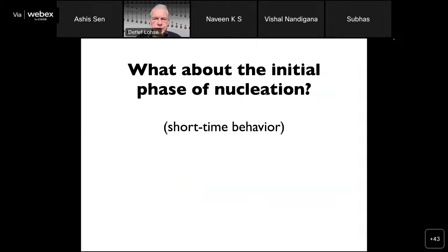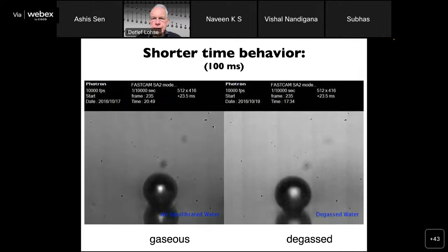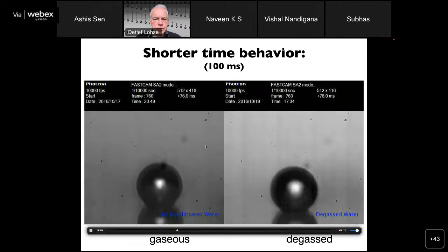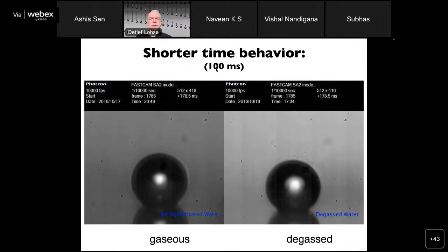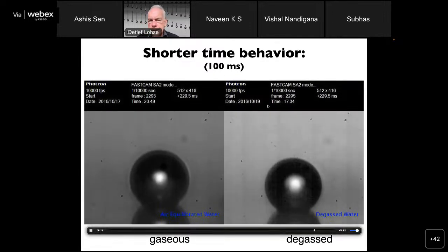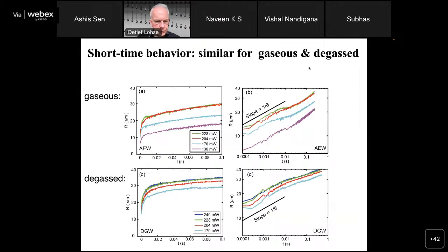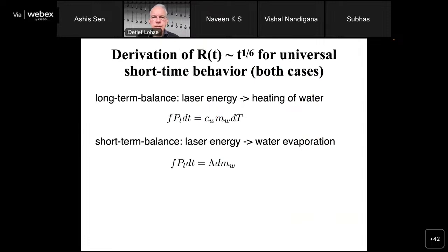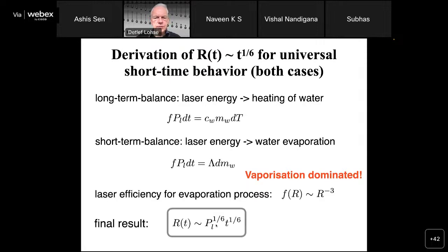So, the initial phase of contact, the short time scale behavior: there's not enough time for the gas to go into the bubble. So for the short time scale behavior, it's now not 5 seconds as before, but 100 milliseconds. I won't go into this because I want to spend time on the others. But they can derive, in fact, that the radius goes like t to the 1/6. For the long time scale, you balance the laser energy with the heating of water; on the short time scale, you balance the laser energy with water evaporation, because it's dominated by evaporation. And when you do all this, you get, in fact, that the radius goes like t to the 1/6.